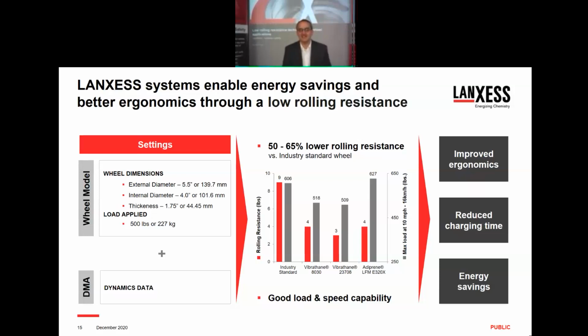So again, the industry standard has very good load capability and a significantly higher rolling resistance compared to these special urethanes, these low rolling resistance urethanes. The Vibrathane 8030 has a rolling resistance of 4 compared to 9, so we're cutting that about in half. Again, that was the polycaprolactone. We do drop a little bit of the capacity there, but again, over that 500 requirement.